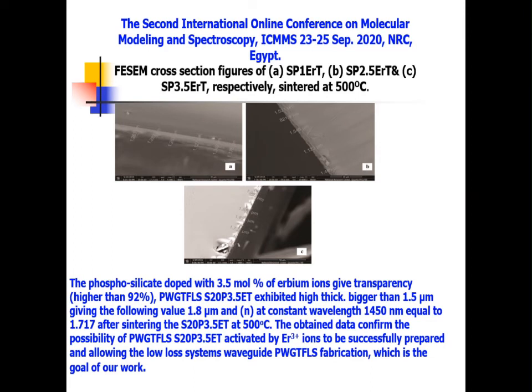And this sample was studied by field emission scanning electron microscope, and we found it has a thickness of 1.5 micrometer up to 1.8 micrometer, and its refractive index at a wavelength of 1450 nanometer equals 1.7 after sintering this planar waveguide thin film layer system at 500 degrees centigrade. The obtained data confirms the possibility of this waveguide activated by erbium ion to be successfully prepared, allowing low loss waveguide fabrication, which is the goal of our work.